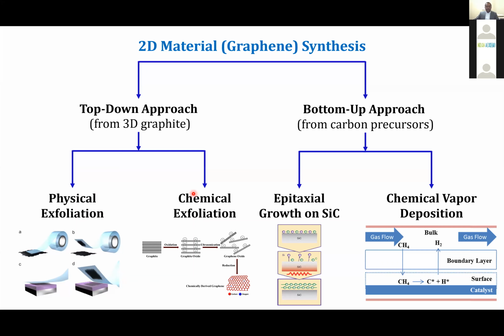So therefore, we have chemical exfoliation, where we can take graphite and use strong oxidizing agents like sulfuric acid or KMnO4, and then oxidize. It's a chemical process called oxidation, where the oxidizing agents can intercalate into the layers in graphite, so that the van der Waals bond becomes even weaker, and then we can use a sonicator to sonicate these weakly bonded graphite layers to exfoliate them in a solution process.